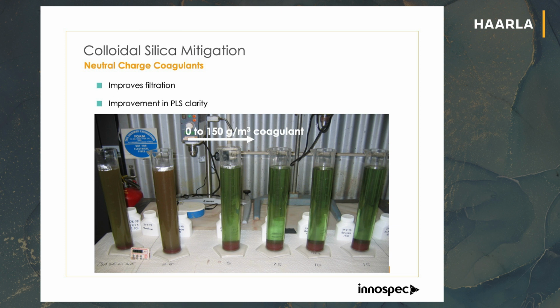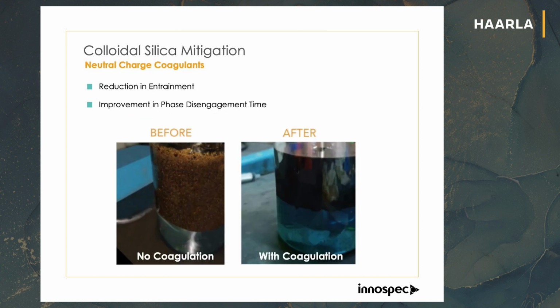The other thing you're looking at is in the solvent extraction phase, the separation that you get, or the disengagement. If you look at your interface between the water and the organic phase, that is separating more effectively. You can't see it very well, but you've got a nice blue layer at the bottom, whereas it's continuous here. You don't see any difference. And that's very, very important.